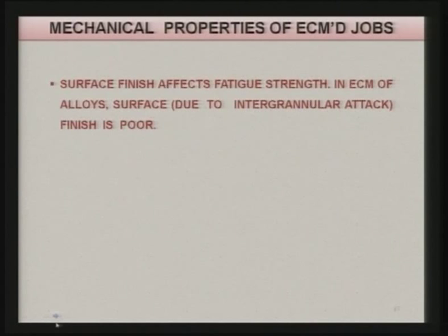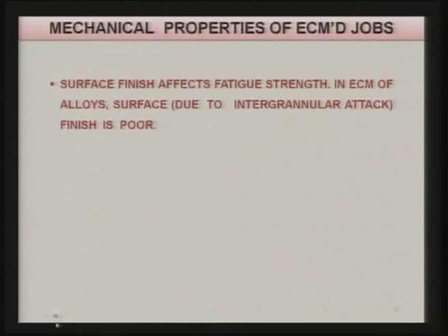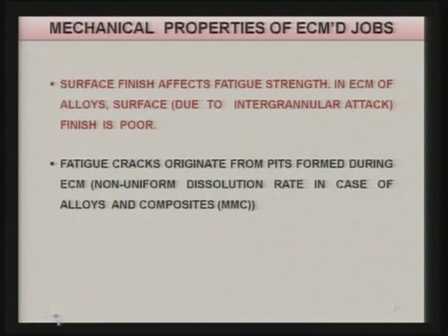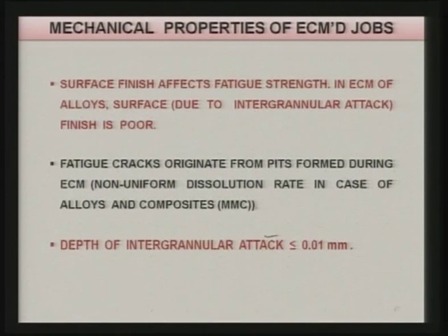Surface finish affects fatigue strength. In ECM of alloys, intergranular attack results in poor surface finish, which also reduces fatigue strength because high attack on intergranular boundaries removes more material from the boundary and forms micro-pits. Fatigue cracks originate from these pits formed during electrochemical machining and from non-uniform dissolution in alloys and metal matrix composites. Depth of intergranular attack is normally equal to or less than 10 micrometers (0.01 mm), and these are the main causes of reduced fatigue strength.